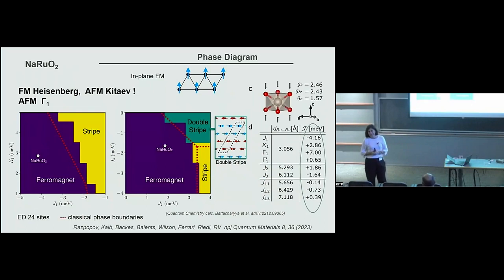And don't you consider some sort of random singlet? Because ruthenium oxide is famous for this very strong dimer formation. At least the structures that we get from Stephen don't have any distortion. He has done X-ray data, and it's a very nice triangular lattice. There is no distortion there. So at least from the structural data that we have, there is no signature of this type of distortion. But yes, we need to work out this susceptibility.